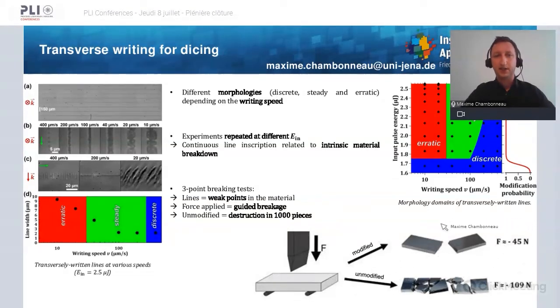And besides, we have carried out some three-point breaking tests, as illustrated here, and we have seen that the lines act as weak points inside the material, meaning that the breakage is basically guided when a force is applied. In contrast, when the wafer is not modified and you try to do this kind of three-point bending test, then the wafer is destroyed in 1,000 pieces.